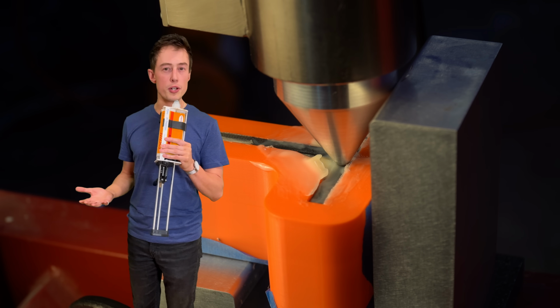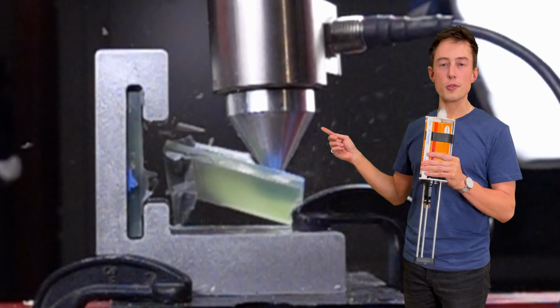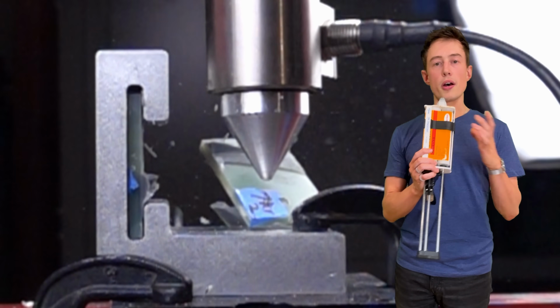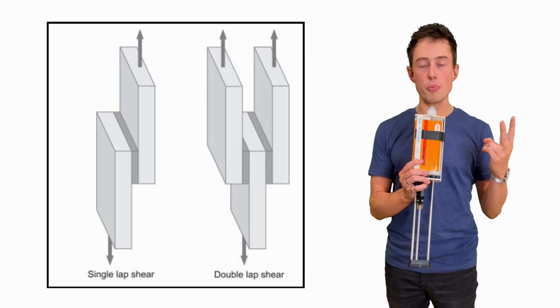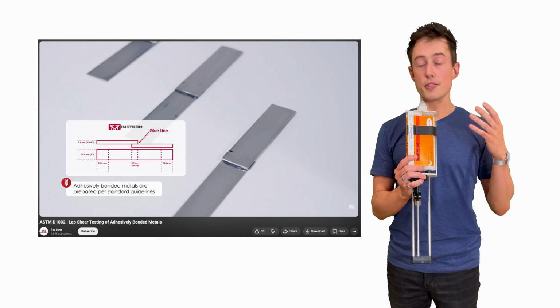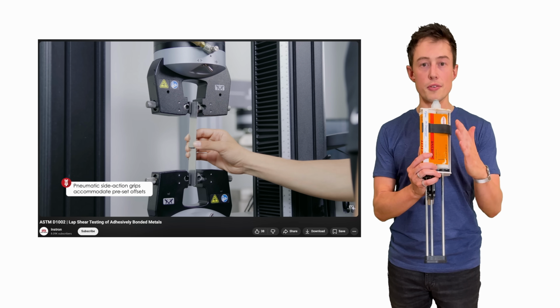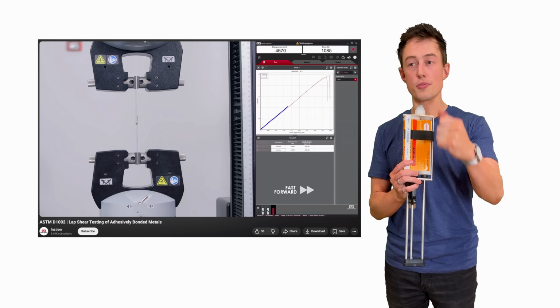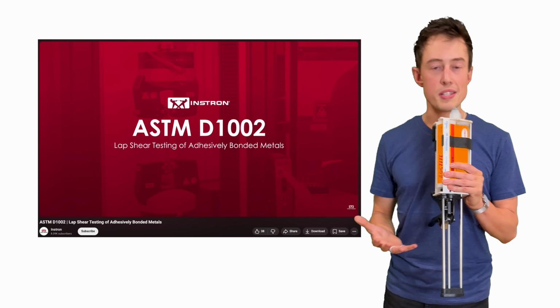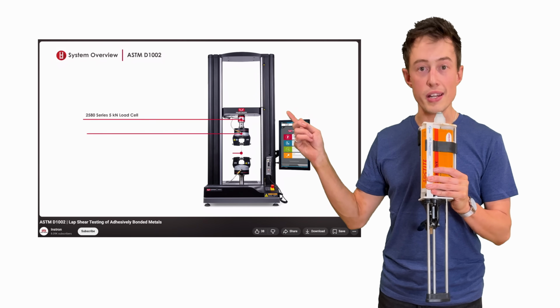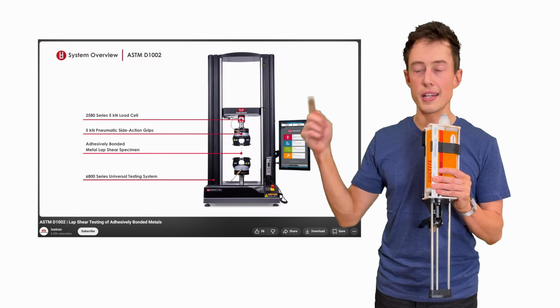You might be wondering by now why we're setting up the test coupons this way. Most composite bond testing is run as single or double lap shear tests. That's where you take the two pieces and press the flat plates together, then pull them apart lengthwise and measure the stress and strain. Oftentimes this is done with a fancy machine called an Instron, and you're getting way higher fidelity data than anything we're doing here.